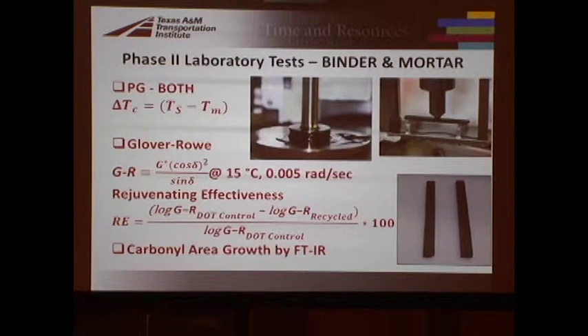Then we came up with an initial idea, and I'll show you on a plot, to look at what we call rejuvenating effectiveness. We sort of had an initial rejuvenating effectiveness as the Glover-Rowe parameter for that DOT control mix minus the Glover-Rowe parameter for the recycled mix that was shown on the right of the previous slide, divided by the DOT control one, and all those are log values.